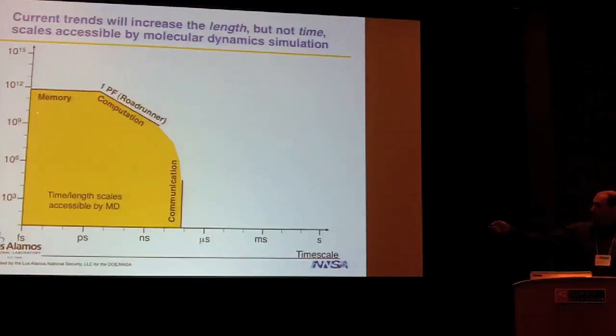Of course, there's not much interesting that happens within a trillion atom sample in a few femtoseconds or even up to a picosecond. So we typically trade off system size, take advantage of this order n scaling to model smaller systems for longer times. So this gives us some linear scaling region. But eventually, as we do this, and the computational time step is in wall clock time shorter and shorter, we're eventually constrained by the overhead for each time step, just due to the communication and the synchronization, the barriers between processors. So there's a communication wall at some point, and this is just roughly what we could do on a typical system in 1 day of simulation.